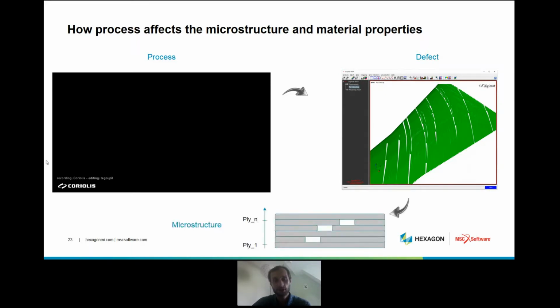Hopefully there are defects that we can predict quite easily, because it's already information that we can extract from the manufacturing software that allows us to prepare this kind of process. So we'll be looking in the next slides at understanding these defects better, mainly gaps for today. As you can see in this cross section, when parts of composite material are not present due to the defects, this will introduce either a local reduction of thickness or a reduction of the fiber volume fraction. In any case, this will directly affect the local material properties and have an impact on the actual real part performance.